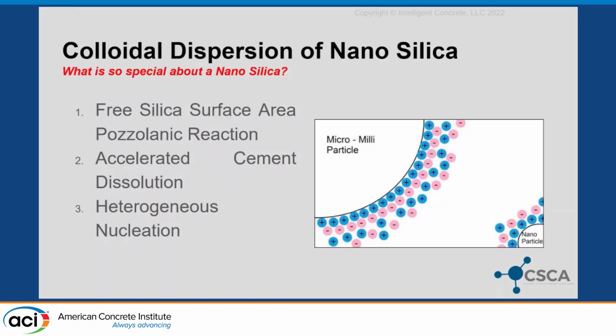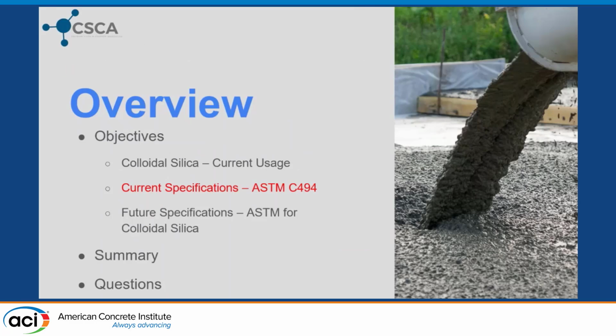Now, because there are more reactions, we see this accelerated cement dissolution. There's a wonderful paper written back in 2003, and another one in 2004, by Bjorn Bjornstrom that goes into this phenomenon. And then the last thing is a really fancy name, heterogeneous nucleation. What we're trying to say is really small things will encourage other things to grow on them. Ultimately, that's what we're seeing with our nanoparticles in solution. They have a much smaller force field in suspension as opposed to a micron-sized particle, so things will want to grow on its surface.